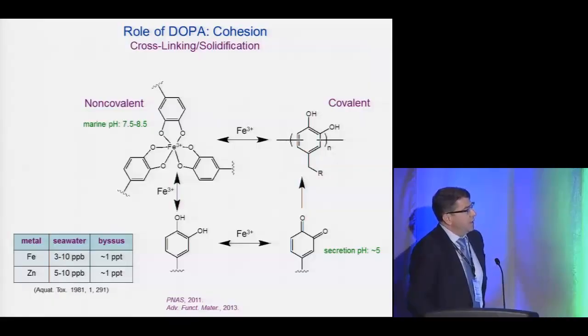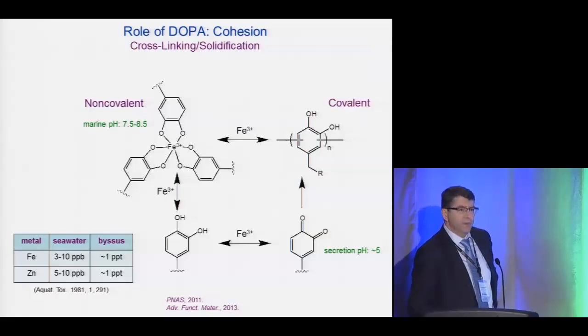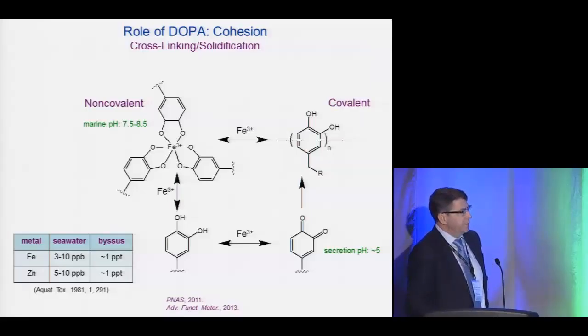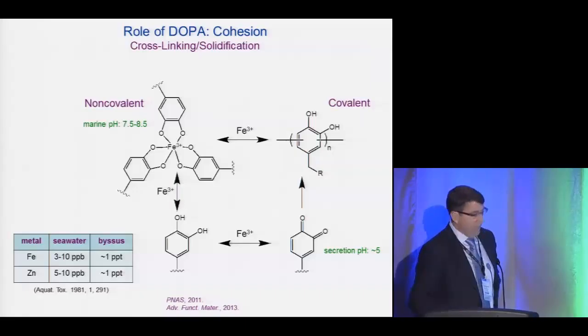Okay? And here's where more recently in our group as well as other groups, we've been able to show that actually through redox reactions, iron is involved in this oxidation, which gives rise to covalent cross-linking. And this happens under a secretion pH, which is acidic. And iron is also involved in the formation of mechanically active coordination bonds that look like this. They're tris coordination bonds between one iron atom and 3 catechols. And this is favored at marine pH, this type of coordination between iron and catechols. This catechol functional group is very well known in the literature for its strong affinity for transition metals. And this interaction here is mechanically active.